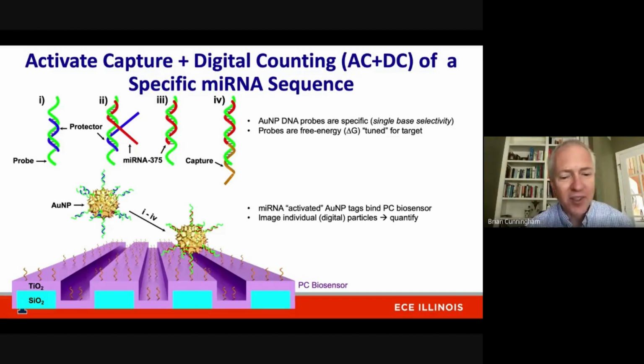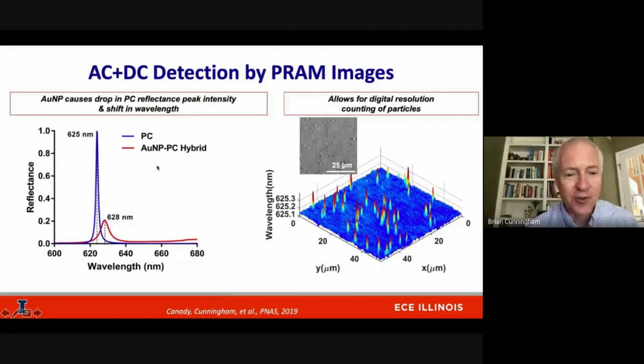I won't say too much about this because it's really the topic of molecular biology, but these toehold probes are very selective. You can design them using thermodynamic principles to only recognize the target microRNA sequence. In this case, our old friend microRNA 375, and then not any others. And so in this way, each gold nanourchin that's captured reduces the reflected intensity from high to pretty low, as shown here. And so basically the photonic crystal is giving us an enhanced form of contrast for detecting and then counting those gold nanourchin nanoparticles.